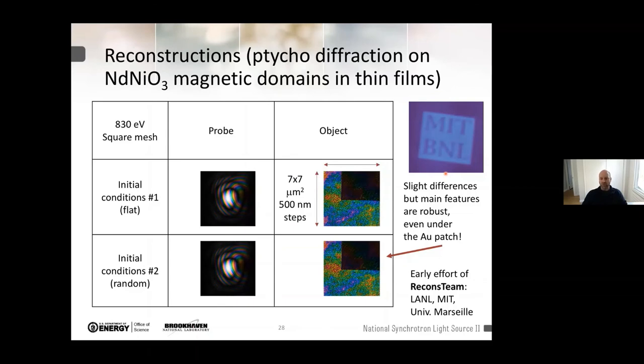out of the coherent images that are formed through speckles at the detector, and apart from a nice, let's say, test case, just to prove that you have submicron resolution, you can actually detect structural and magnetic relevant information across your sample, even when it's partially covered by a gold slab that is used as a reference, just to have a sharp corner or things like that. But it's only partially transparent, partially attenuating the signal, so you can even see that you're able to reconstruct all the underneath. And so to check that the presence of a metal close to the surface does not perturb in a specific way the ordering you are considering.